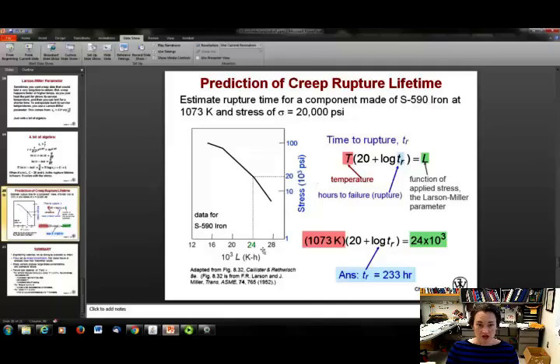Okay, so if you go to the stress you're looking at, which is 20,000 psi, and you go over to your curve, then you can read off what your Larson-Miller parameter is there. And it's 24 times 10 to the 3. Okay, so then you plug in 24 times 10 to the 3 for your Larson-Miller parameter. You plug in your temperature there on the left-hand side, and then you solve for that log of the time to rupture. And the time to rupture, once you get rid of that log, is 233 hours. So you can check that out.